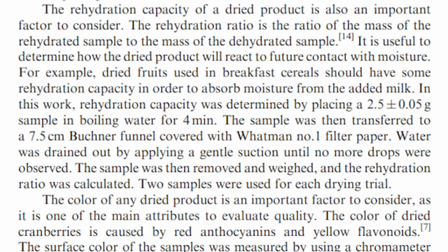The rehydration capacity of a dried product is also an important factor to consider. Rehydration ratio is the ratio of the mass of the rehydrated sample to the mass of the dehydrated sample. It is useful to determine how the dried product will react to future contact with moisture. For example, dried fruits used in breakfast cereals should have some rehydration capacity in order to absorb moisture from the added milk. In this work, rehydration capacity was determined by placing 2.5 ± 0.05 grams of sample in boiling water for 4 minutes. The sample was then transferred to a 7.5 centimeter Buchner funnel with a Whatman No. 1 filter paper. Water was drained out by applying a gentle suction until no more drops were observed. The sample was then removed and weighed, and the rehydration ratio was calculated. 2 samples were used for each drying trial.